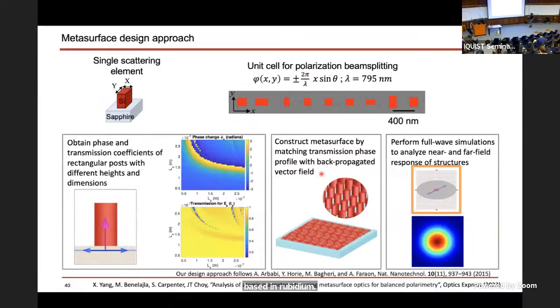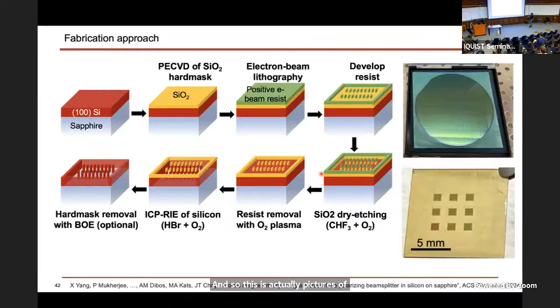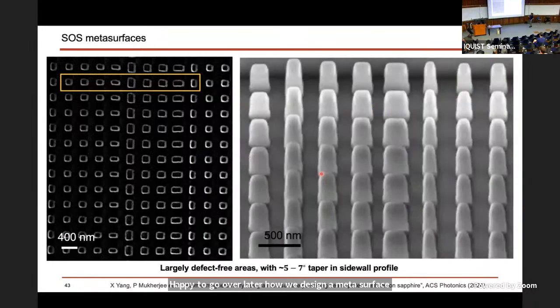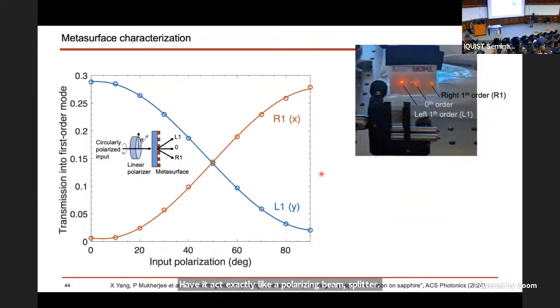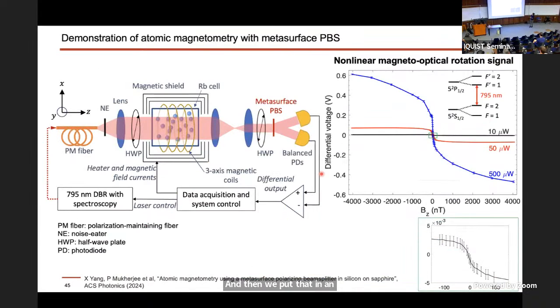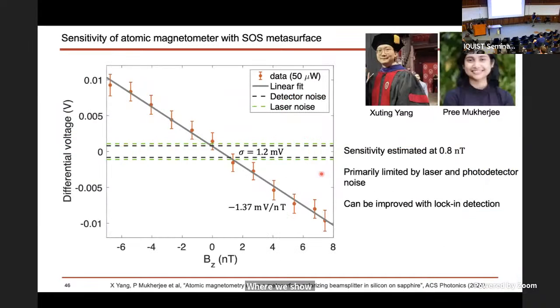And so this is actually a picture. I'm happy to go over later how we designed a metasurface. But basically, we made a metasurface comprising these silicon pillars on a transparent substrate, in which the idea is to have it act exactly like a polarizing beam splitter. And then we put that in an atomic magnetometer setup where we show magnetic sensitivity of below a nanotesla.